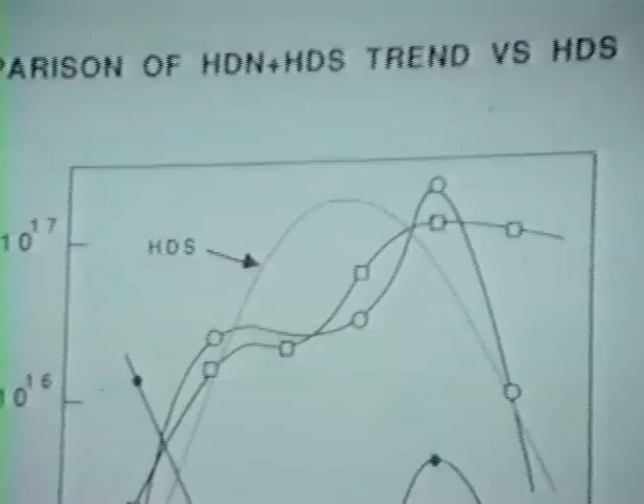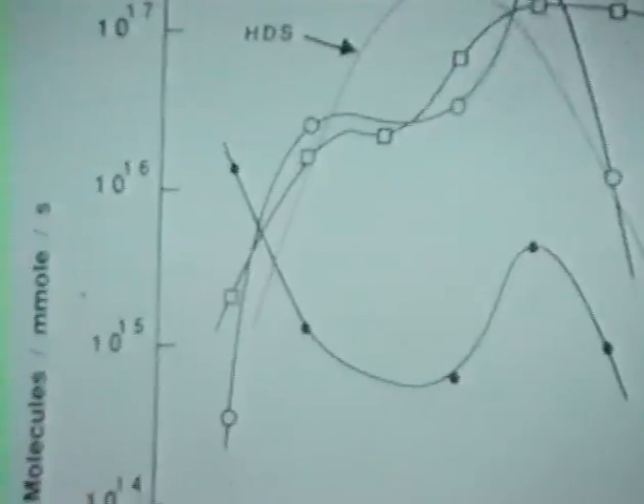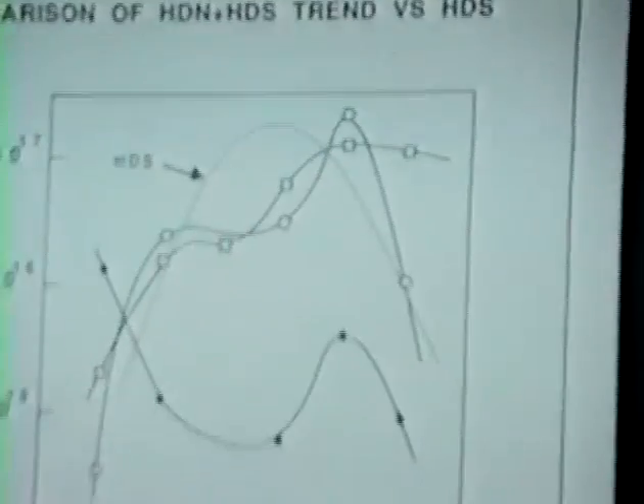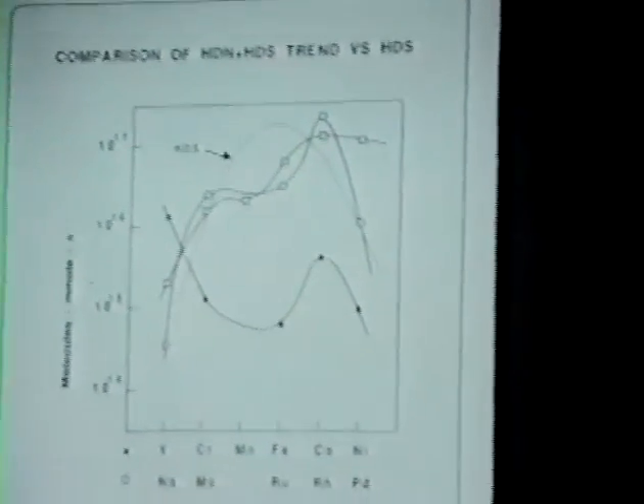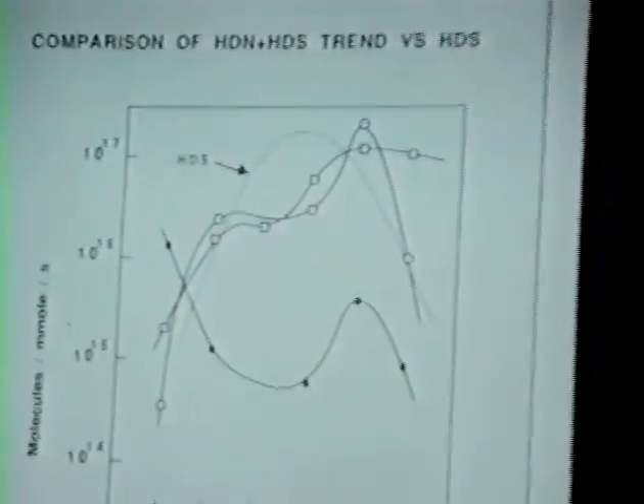It simply shows you that when you're doing the HDS and HDN equivalent - here what I'm doing is summing the carbon-nitrogen and carbon-sulfur total bond breaking activity - the thing I'd like you to keep in mind is, as you can see comparing them against the trend I showed before, the sum rate for these very active noble metals is essentially the same when you put nitrogen into the system. This is an entire other topic, the HDN, which I don't have time for today.